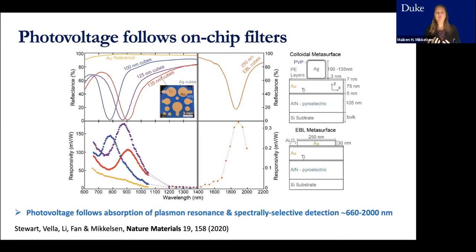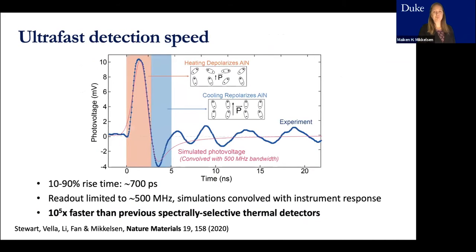But I think the real beauty of this is that there's really no limitation on the wavelengths here. It's a thermal detector. We can make nanoscale structures to absorb at any wavelength. So you could have a very beautiful detector that could be sensitive across the entire wavelength range, theoretically. So we thought that was a nice demonstration, but what was really the surprise in these experiments was that we could see that the photo response was also fast.